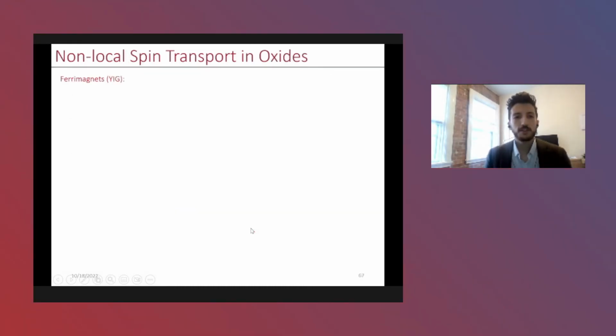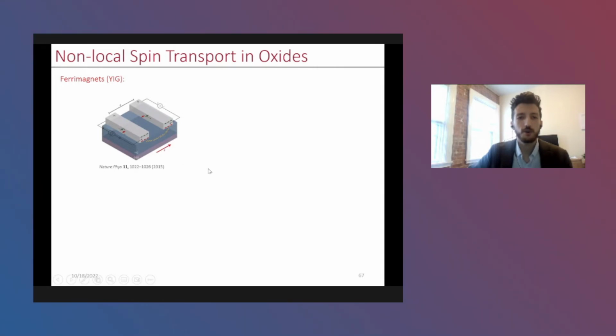And so a popular way that these are exploited, particularly once again in garnet materials because of their low damping, is by using what's called a non-local spin transport geometry, whereby on the surface of one of these films, you pattern electrodes that are typically metallic, in this case using platinum. It's both a spin source and a spin drain or spin sink. And I mentioned various excitation mechanisms of spin waves. Using this sort of geometry, you can excite spin waves in two different ways. One by using the spin Hall effect, or what they call a spin flip scattering mechanism. It's angular momentum that gets accumulated at the interface, can cause spin wave generation.